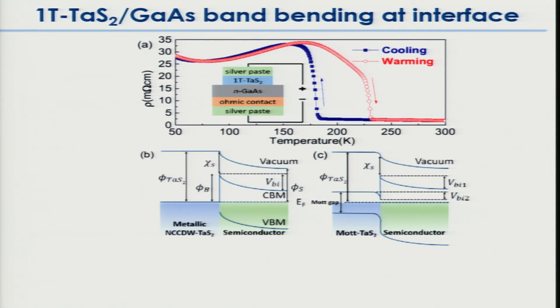But what we're doing now is making Schottky diodes out of these by just taking the N-type gallium arsenide, freshly cleaved, doing the same thing with the tantalum disulfide, pushing it down, and using silver paste. And this is the structure. This is the band structure that we're expecting. This is the semiconducting metallic phase where you have the built-in potential in a semiconductor.